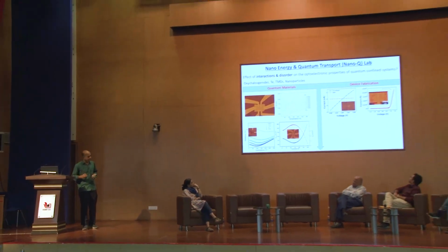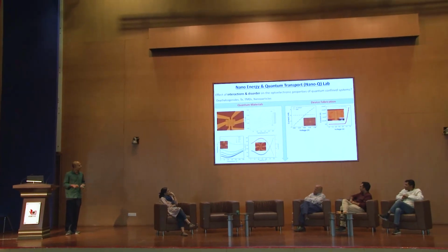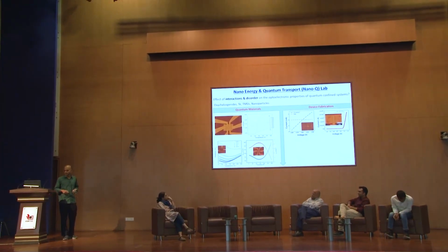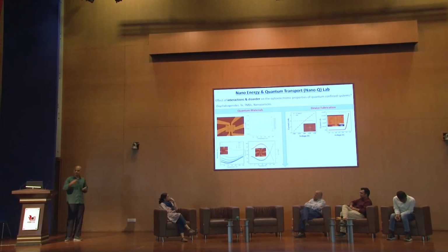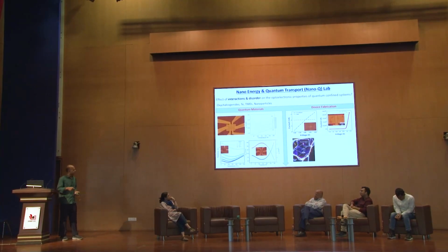And here what we found is that once we make a top gate, the mobility that we are getting is kind of reaching the theoretical mobility of MoS2. Theoretical mobility is 400 centimeters squared per volt second, and what we are getting is 385. Okay, so it's again because of the device fabrication challenge.